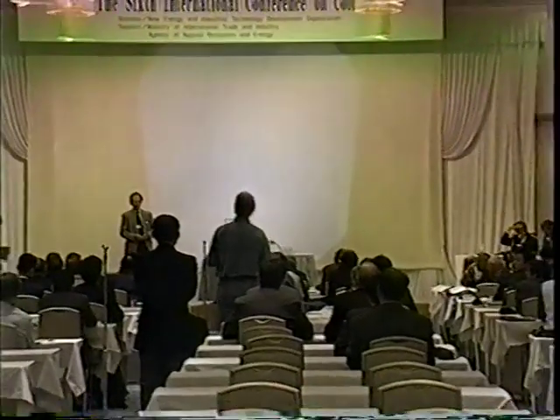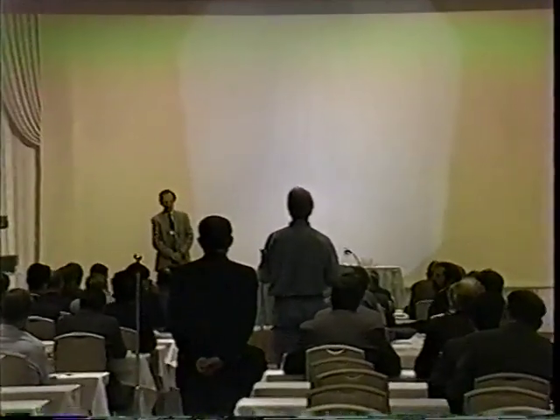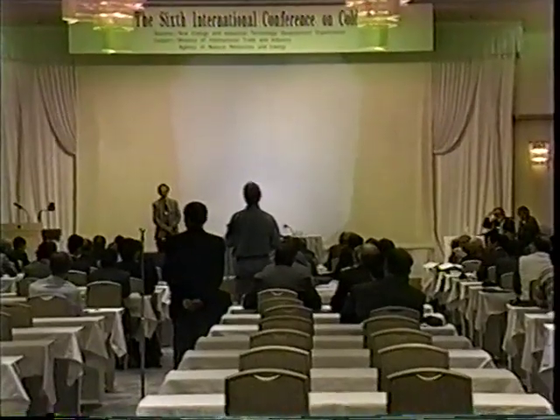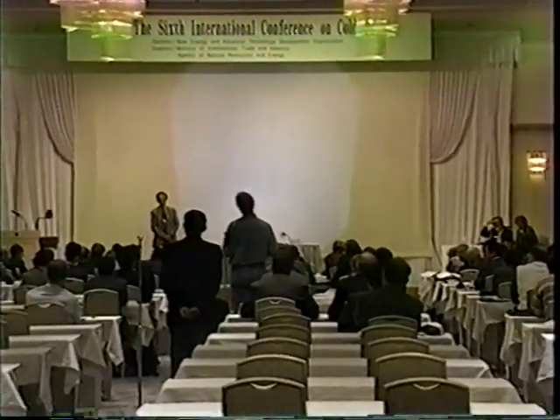First of all, Vittorio, that's a wonderful paper. I congratulate you on very useful work. Let me introduce another factor though. When you go through the high-low cycling process, you also have the possibility of depositing species on the surface which affect the absorption. I did a model of the Takahashi cycle in the presence of lithium in the electrolyte. And what probably happens is, at the very high current levels, you deposit lithium, which impedes the ingress of deuterium. You go to the lower current level, the lithium leaves the surface, leaving the surface free to absorb. So the stress is clearly important and produces, I think, the results that you described, but also the absorption and desorption of species from the electrolyte will produce similar effects.